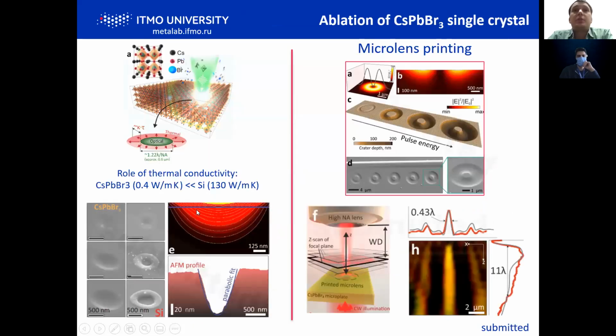And in the very end, I will show some recent results, where we can also ablate single crystal perovskites. Here you see the direct comparison with silicon, which has much higher thermal conductivity. You see almost 2.5 orders of magnitude difference. Ablation of perovskites gives very clean and smooth craters, whereas for silicon, due to overheating of the remaining areas and the long lifetime of the melted area, we see damage and ugly craters. But this allows us to create high quality micro lens printing by shaping of the beam. We also studied the properties of these micro lenses made of excitonic perovskite, and we see very good quality of focusing.